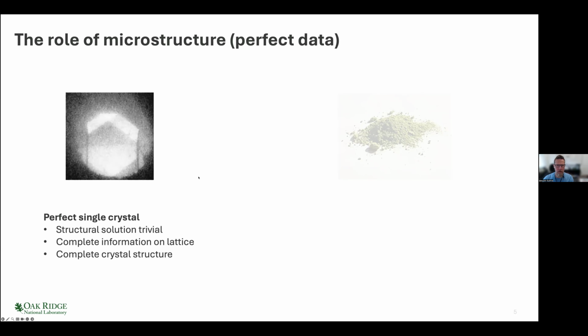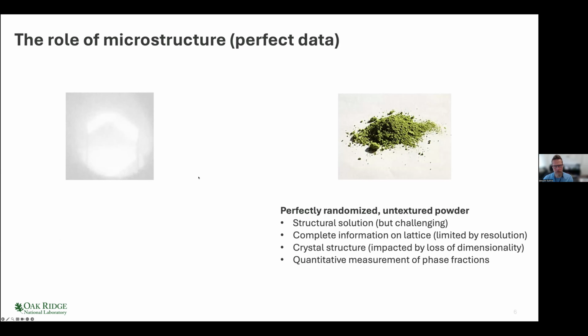And as I mentioned, another approach is to use a perfectly randomized, untextured powder. And you can go very far with that as well. You can completely solve a structure, although it's a little more challenging than the single crystal case because your information has gone from 3 dimensions to 1 dimension. You can get complete information on the lattice, again, limited by the overlapping that comes from collapsing 3D down to 1D, and then the limit of the resolution of your instrument, which may lead to peaks which have a different D spacing being merged because the peaks are too broad.